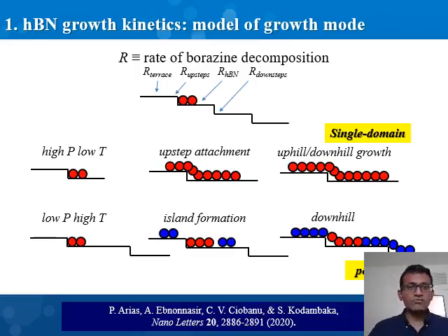growth related aspects. So if we consider the rate of borazine decomposition, the borazine needs to dissociatively chemisorb on the surface, and this can happen by one or more of the following four aspects. The deposition can occur directly on the terrace, at the up steps, at the down steps, and also at the already deposited hexagonal boron nitride step edges. And each of these arrows is intentionally marked with different lengths that is indicative of what we think are the increased rates of deposition.